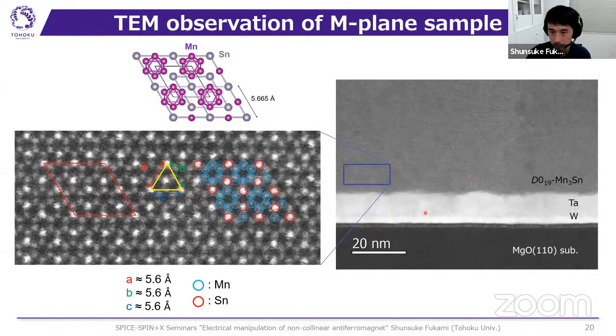Okay, and this shows the cross-sectional TEM image of the M-plane oriented samples. This shows the low magnification image, and you can see the MgO substrate, tungsten-tantalum, and D0_19 Mn3Sn. And this shows the magnified, high resolution image. You can see that the dark hexagonal spots are surrounded by the bright hexagonal spots, which is nothing but the ordered structure of D0_19 Mn3Sn, the 0001 plane of the Mn3Sn, or the Kagome plane of the Mn3Sn. So a very nice epitaxial thin film was formed by this stack structure.